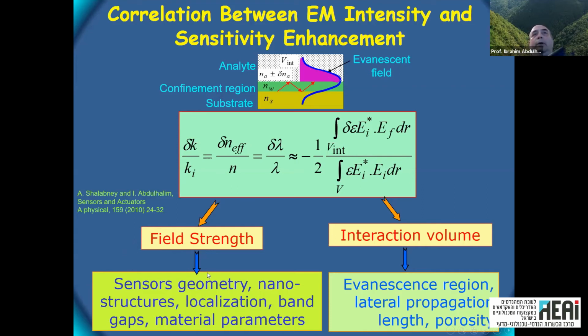Which is determined by the geometry of the sensor, a nanostructure, localization, could be band gaps, material parameters, and so on, and also the interaction volume. So it means the penetration depth or the propagation length, or if you have a porous medium, like the metamaterial we just mentioned, what's called porosity of the metal, let's say. We can make a porous metal and it will give us higher sensitivity, which can be explained based on the same integral.